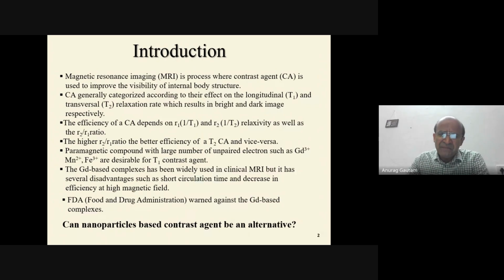And lots of parameters are there to see the differences. Literature also says that for the contrast agent, we report in the form of relaxivity. That is proportional to 1 by T normalized by the concentration of the compound. So we say R1 is proportional to 1 by T divided by the concentration of metal ion. That is called relaxivity. So contrast agents are reported in the form of relaxivity, not in the form of relaxation time. But relaxation time is very important, because the shorter the relaxation time, the higher the relaxivity. The higher the relaxivity, the better the contrast.